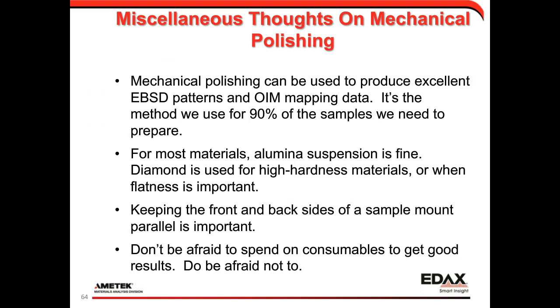So in summary, I've titled this Miscellaneous Thoughts on Mechanical Polishing. Mechanical polishing can be used to produce excellent EBSD patterns and good EBSD-OIM mapping data. It's the method we use for probably 90% of the samples we need to prepare. Part of that's by choice, part of that's just based on what we have available. For most materials, alumina suspension works well. I use diamond only for high hardness or when I need to make sure it keeps flat.